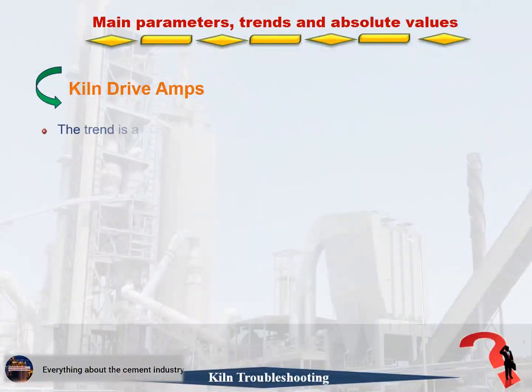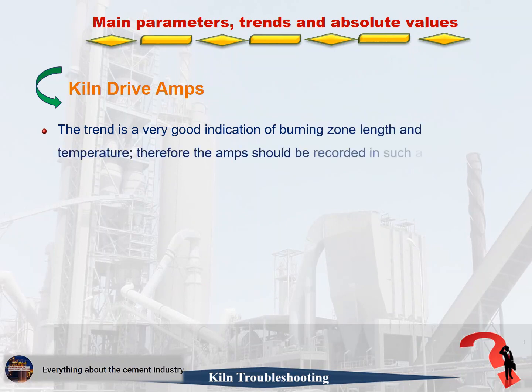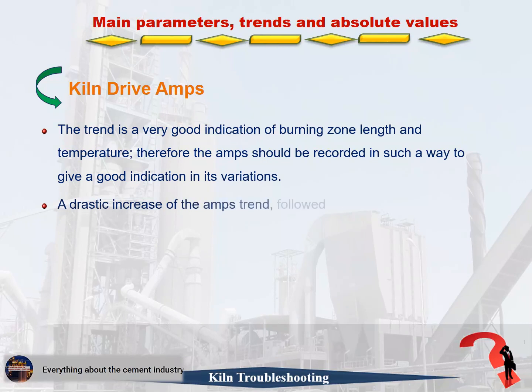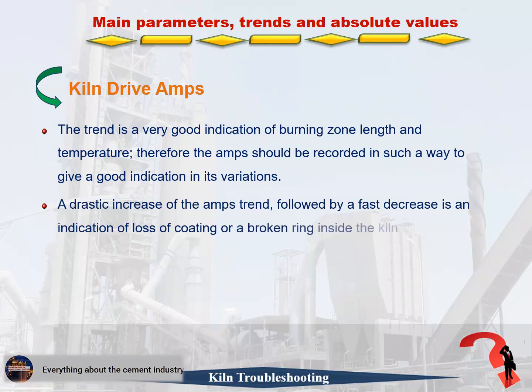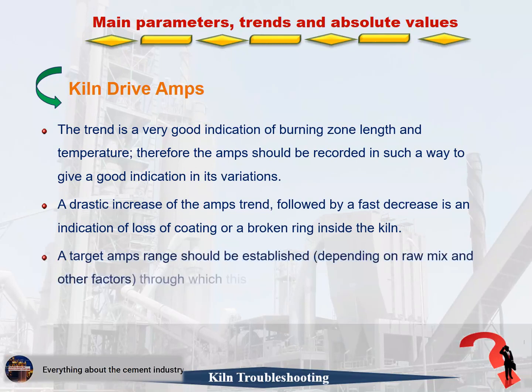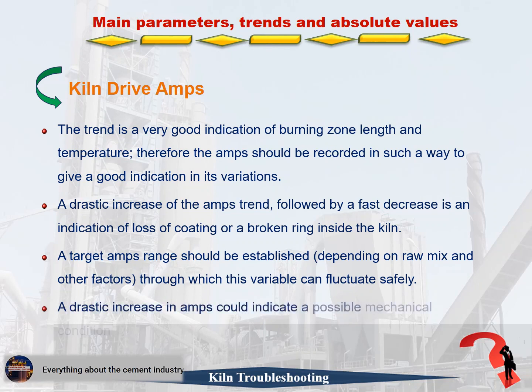6. The trend is a very good indication of burning zone length and temperature, therefore the amps should be recorded in such a way to give a good indication in its variations. 7. A drastic increase of the amps trend, followed by a fast decrease is an indication of loss of coating or a broken ring inside the kiln. 8. A target amps range should be established, depending on raw mix and other factors, through which this variable can fluctuate safely. 9. A drastic increase in amps could indicate a possible mechanical condition problem.